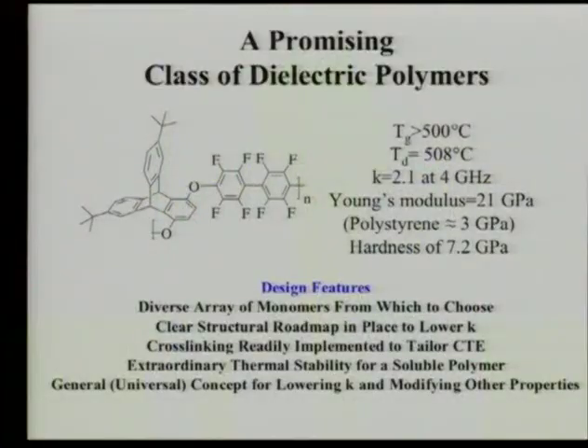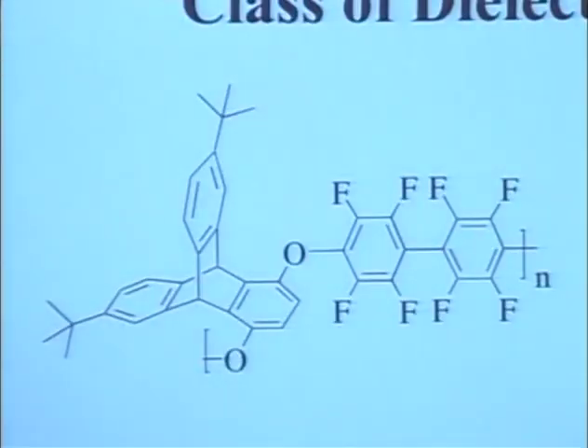And we've done that with a series of materials based on these triptycene materials. Again, we fuse them across ways so the molecule cannot just rotate independently. People have put bulky groups off the sides of polymers before, and it didn't work. This is a case where we use a rigid backbone that's actually a little too big to thread through here, so we keep that free volume up.